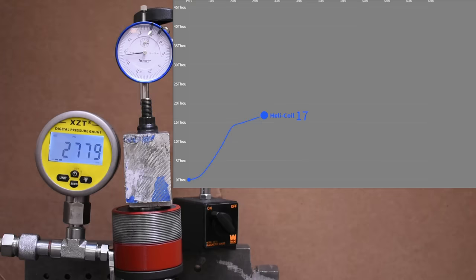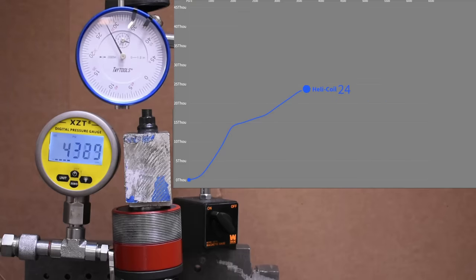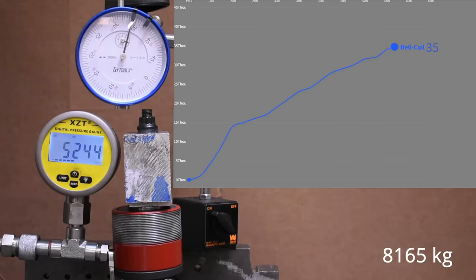With the dial indicator mounted just behind the stud here to measure basically what would be the cylinder head lift from this increasing force, our first stage is increasing things up to 6500 PSI, or about 18,000 pounds, the limit of our hydraulic hand pump here.